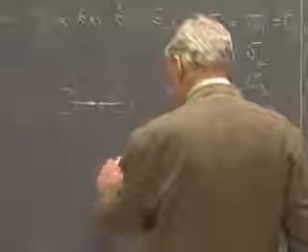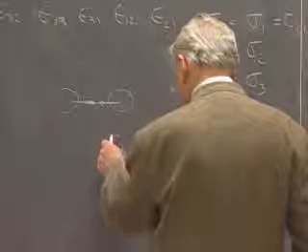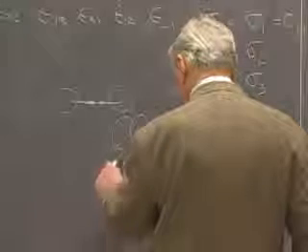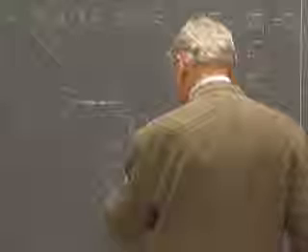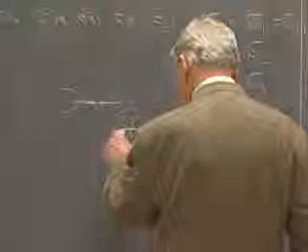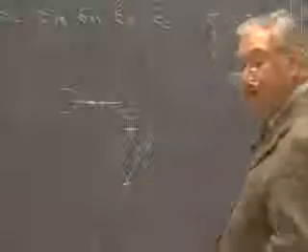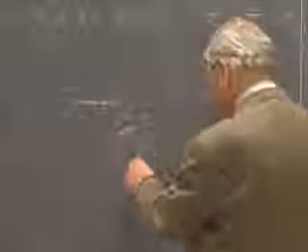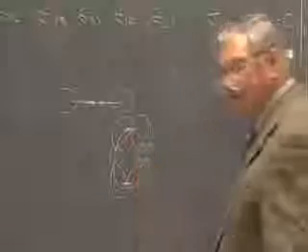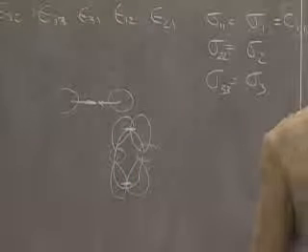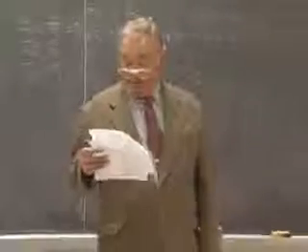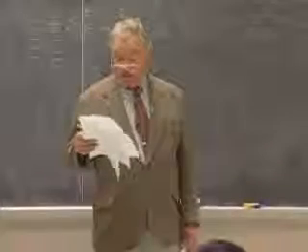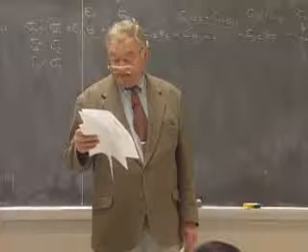But if you had a covalent material where the bonding was due to overlap of orbitals like this, then the thing that holds the crystal together is overlap between these orbitals. And the force holding the atoms together is sort of a force that goes through this shared electron pair, and that's not a central force. And so the Cauchy relation generally fails rather badly for covalently bonded materials.